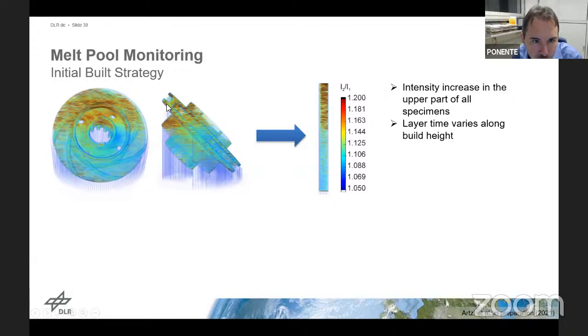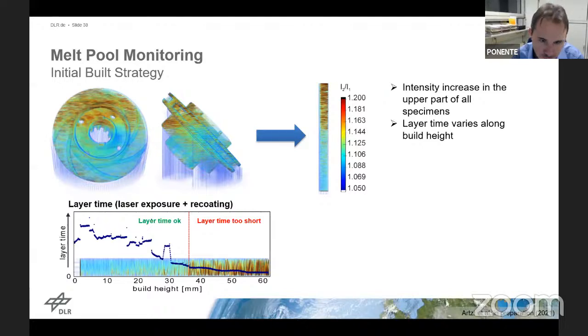At the top of the part, you only have very small parts that still need to be finished. So the laser will finish a layer rather quickly. The layer time is going to be short. When manufacturing this part towards the top, it's going to decrease, meaning with the next layer, the laser comes back to the same spot in much shorter time than at the bottom, and then you get the increased heat input, again, an intrinsic heat treatment, which is not effective at the bottom because your layer time is so high that when the layer comes back to the same spot above the previous layer again, it's already cooled down.